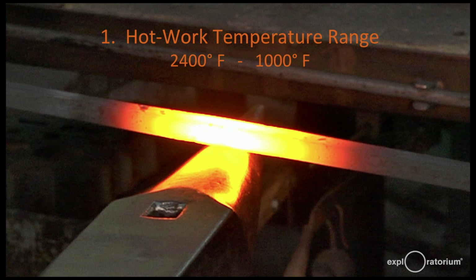even lower than that. There's one additional property associated with the temperature of the iron, and that is that it conducts heat rather poorly, especially compared to the predecessor metal in human history, copper or bronze. What that means is that you can heat a piece of metal up to almost the melting point and maybe 10 inches or 12 inches away, if you work fast anyways, you can be holding onto that bar of metal. So you can be hammering the end of it, holding it with a great deal of control, and that's part of what makes it easy to construct things in the fire.